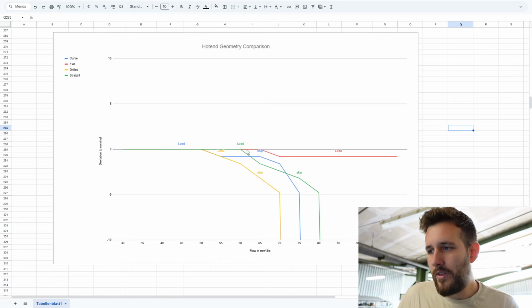So starting off with the straight line, which is represented in green, we can see we managed to get somewhere in the 60 mm3/s range where I could see the visible load. And then somewhere at 75 the extruder started skipping, and then it skipped real hard when I tried to do 80. The yellow line, which I drilled open, you can clearly see that there is a difference shifted to the left. And this is what I've been after, because this is very good news for all of us,